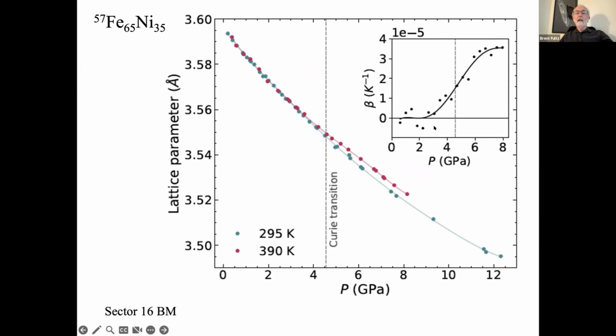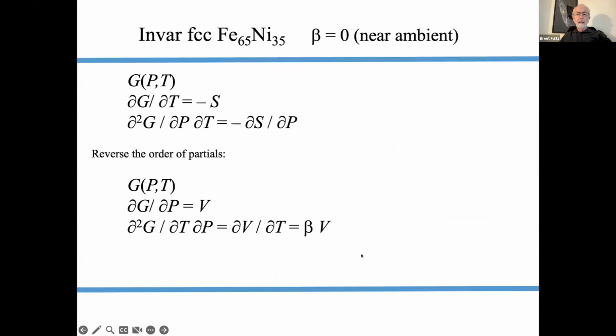We can get a thermal expansion versus pressure out. That's the inset here. And it's not great data, but this is not really what we were aiming to do precisely. But generally, the INVAR effect goes up to about 3 gigapascals. Here's the Curie transition. I'll point that out later. And so it doesn't go all the way up to the Curie transition. Then it gets pretty normal beyond that in the thermal expansion.